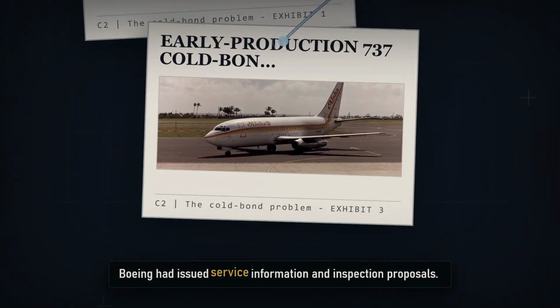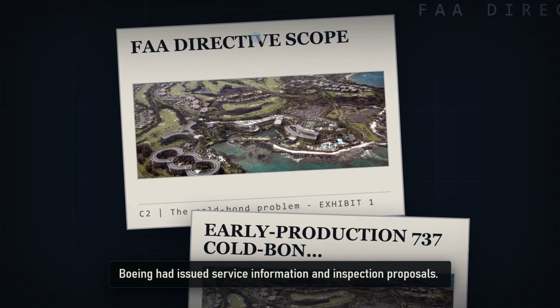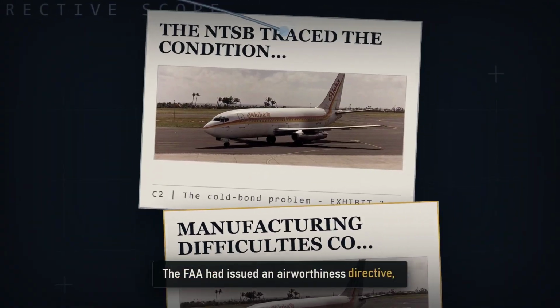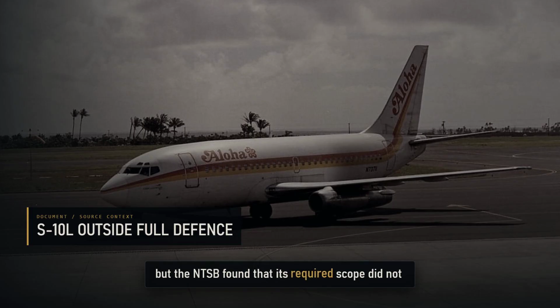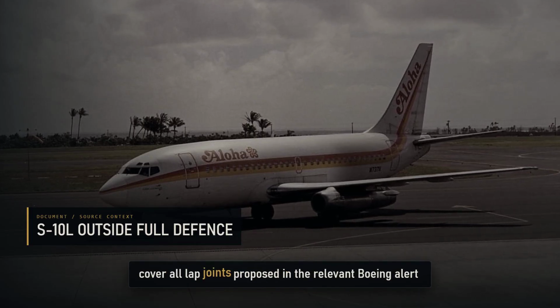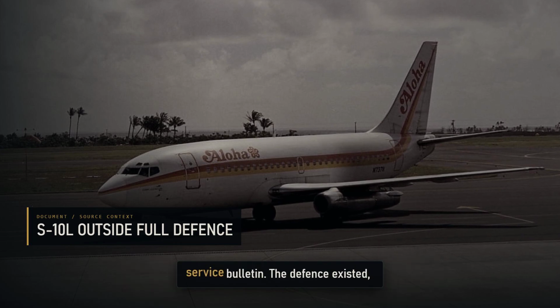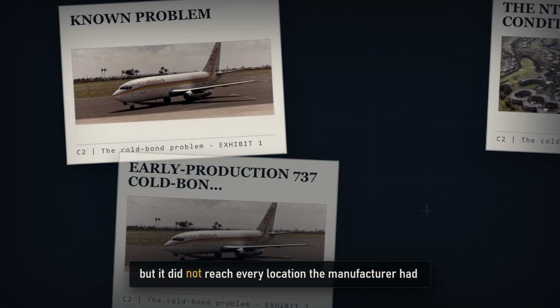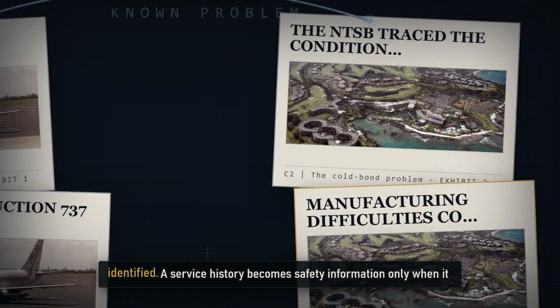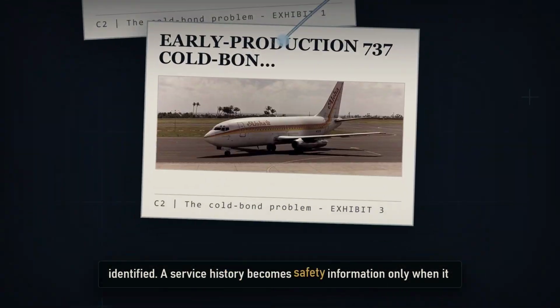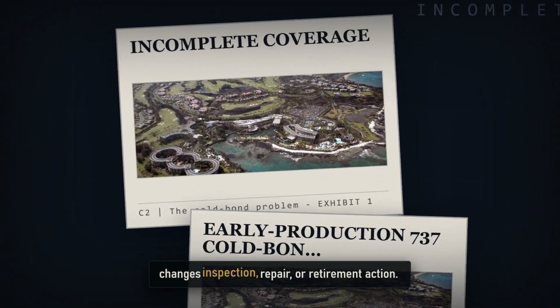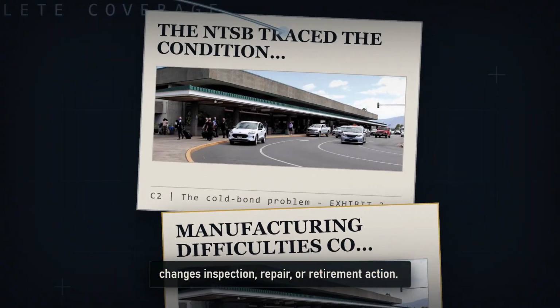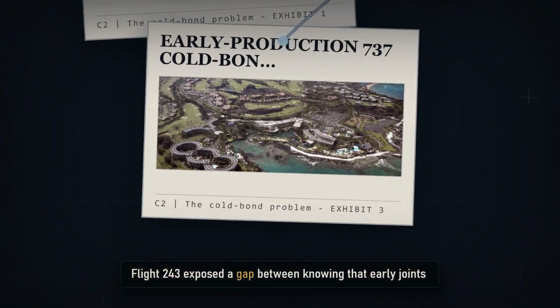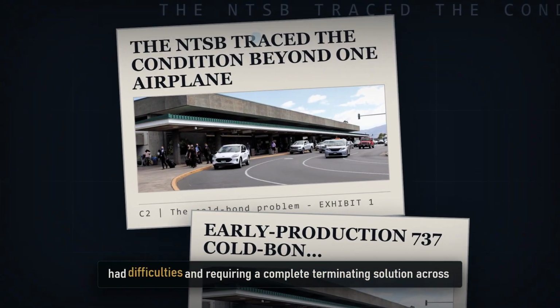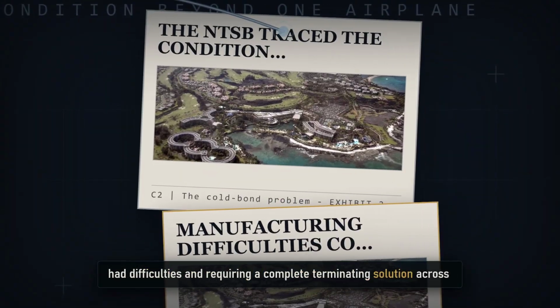Boeing had issued service information and inspection proposals. The FAA had issued an airworthiness directive, but the NTSB found that its required scope did not cover all lap joints proposed in the relevant Boeing Alert Service Bulletin. The defense existed, but it did not reach every location the manufacturer had identified. A service history becomes safety information only when it changes inspection, repair, or retirement action. Flight 243 exposed a gap between knowing that early joints had difficulties and requiring a complete terminating solution across the affected structure.